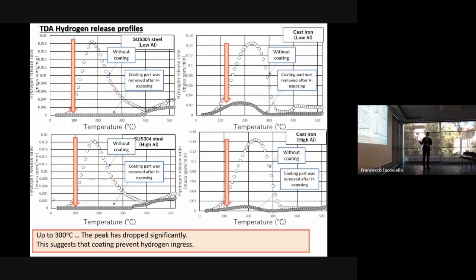Also, this is a cast iron, low aluminum, high aluminum. The peak significantly decreased, but not to zero. A little is left, but this is a very good coating.